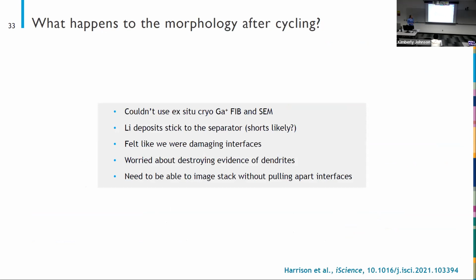We really wanted to look at longer term cycling where we were seeing more of those discrepancies. And we showed this for the low current data where we looked at 50 cycles, but we couldn't use cryo-gallium FIB like we did in that study, because when we tried to take apart these cells to get these ex situ samples for the cryo-FIB process, we really felt like we were having to rip apart these interfaces. And that also made us think that maybe we had some short circuits and lithium growing in the separator. So because we felt like we were damaging those interfaces, we were worried that we were destroying any evidence we might have of dendrites and that this wasn't an appropriate technique to be using.